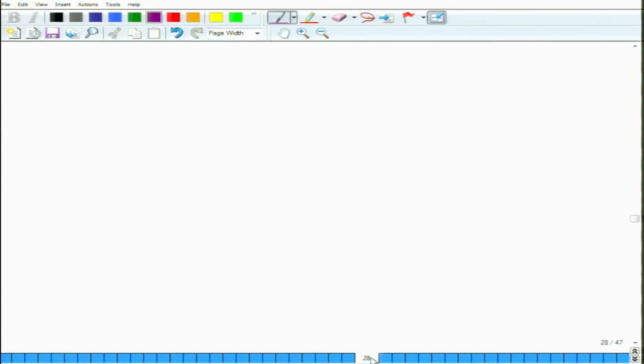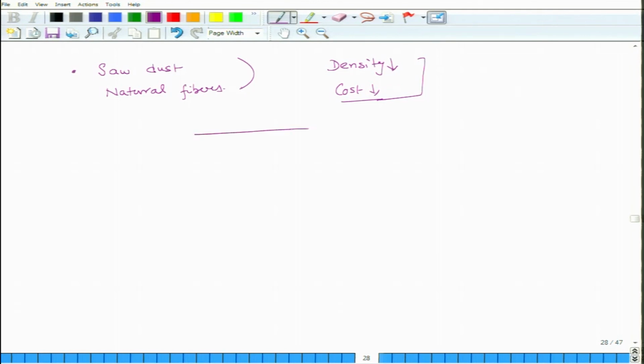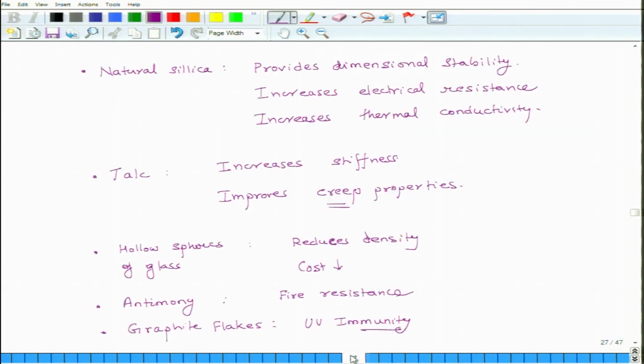And the last filler, and this is getting increasingly used nowadays, can be any one of these: sawdust or natural fibers. Now, the density of wood can be as low as 0.6 to 0.8, 0.9, in that range. So, once you add sawdust to the material, it brings down the density and cost, but a limitation of this is that sawdust and natural fibers absorb a lot of moisture. If you mix it with plastic, the plastic by default absorbs moisture, and now with sawdust it absorbs even more moisture. But these are different additives which we use.